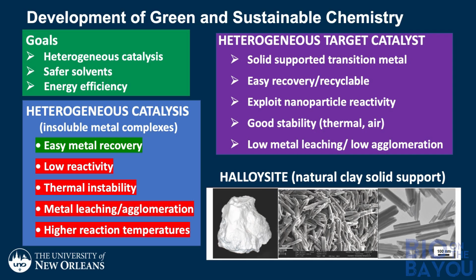Our goal was to essentially develop a heterogeneous catalyst based on a solid supported system that would essentially maximize the use of nanoparticles. Nanoparticles are small particles. They have a high surface area, basically have a much more reactive environment than essentially amorphous materials. And so our approach then was to find a solid support that would exploit our nanoparticle chemistry. And to that end, we began looking at the clay halloysite. Now, halloysite is a natural clay. It's mined out in Utah, and it comes out of the ground looking like this chalk, but it has this fibrous material, which are actually nanotubes.